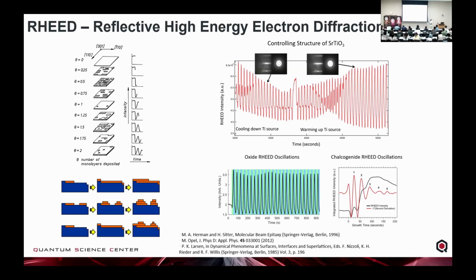And so, a lot of the oxides will grow in this mode. A lot of the chalcogenide materials that we're interested in, you can see some of these RHEED oscillations, but there is going to be a little bit of surface roughness as you start to grow the material. And so some of these oscillations will die out. There'll be a few unit cells of steps, but still overall globally, it's incredibly flat, incredibly uniform across the entire substrate. But here we can actually use this information to understand the structure and the properties.